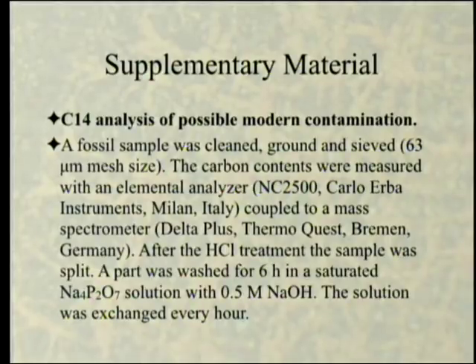After the hydrochloric acid treatment, this is like really high hydrochloric acid. Like 1 molar or better. The sample was split. A part of it was washed for 6 hours in a saturated sodium pyrophosphate solution with 0.5 molar sodium hydroxide. 0.5 molar, so molecular weight of sodium hydroxide is 40, so this is like 20 grams per, this is like about 2% sodium hydroxide. That'll eat your skin off. The solution was changed every hour, so they're really trying to get rid of any contaminants.